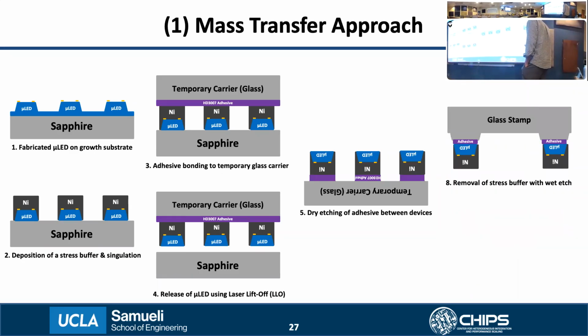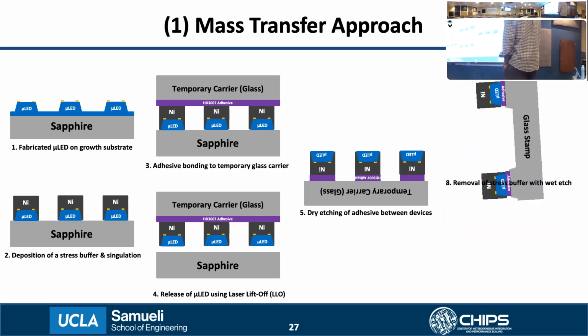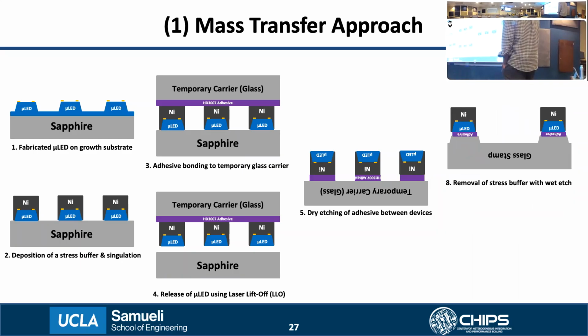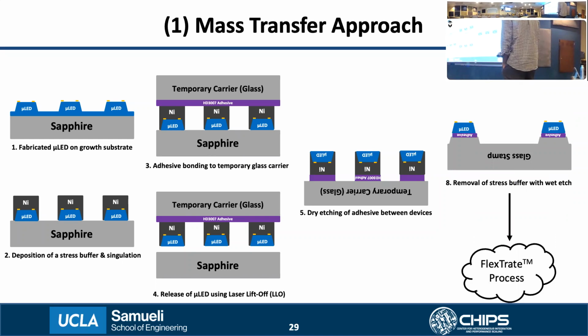which is what you see here. And then once the LEDs are sitting on the stamp, we can clean the surface and also wet etch or remove the nickel layer on top, so that we have these LEDs with the contacts exposed sitting face up on the stamp, on top of which we can do some testing before assembly on FlexTrate. So this is the mass transfer process for taking the LEDs from the sapphire and placing them on the stamp. So any questions?